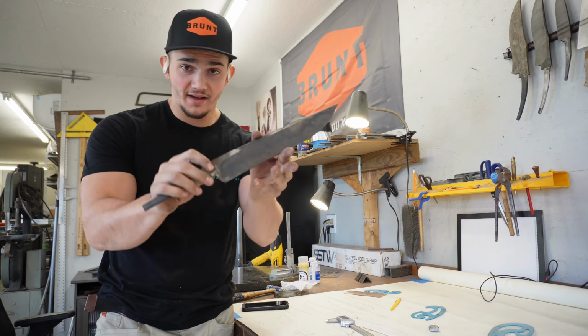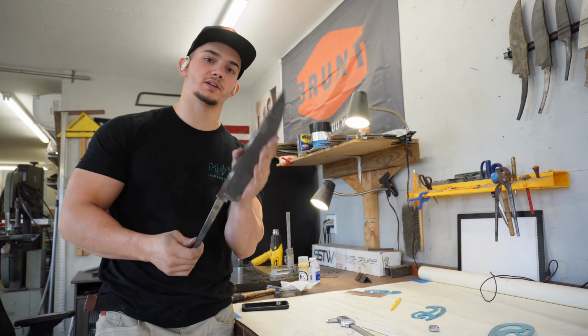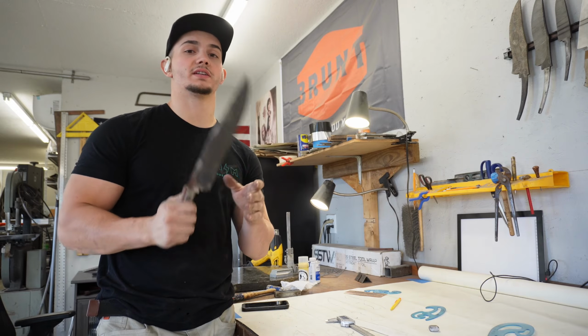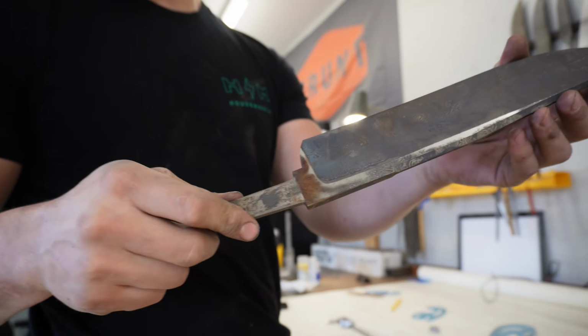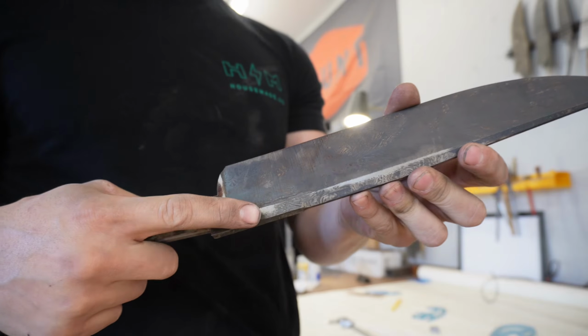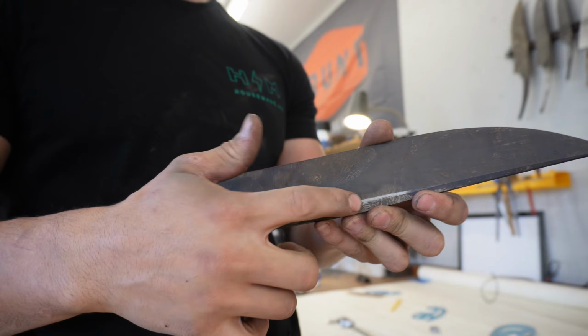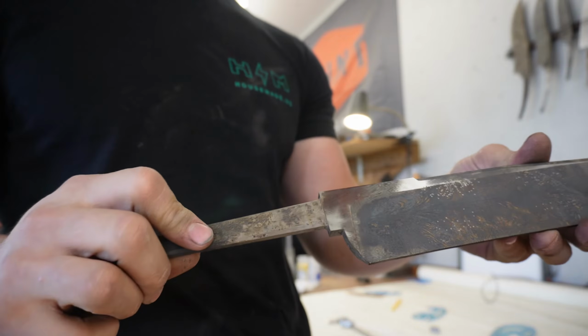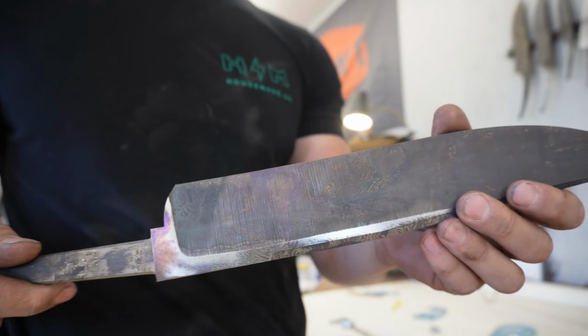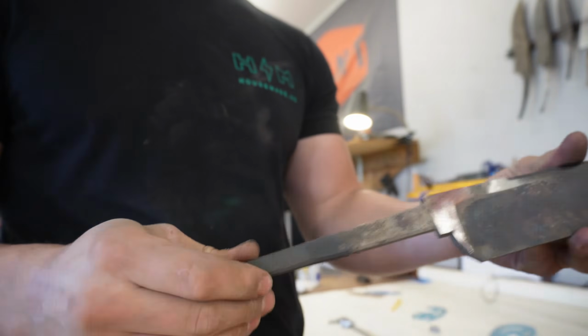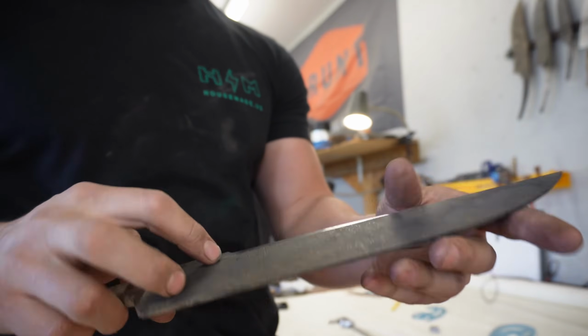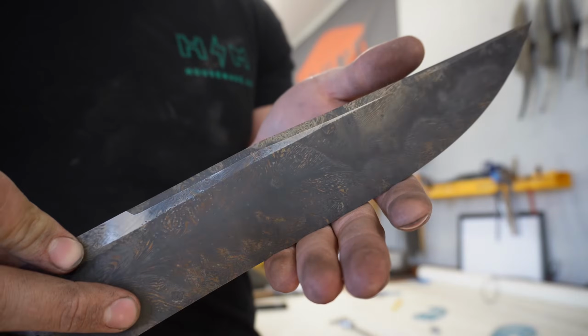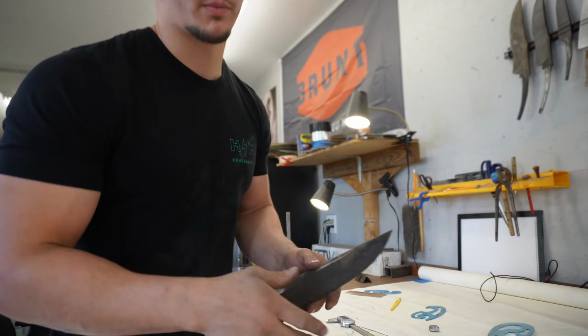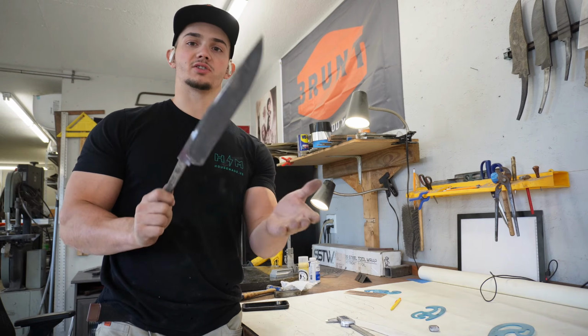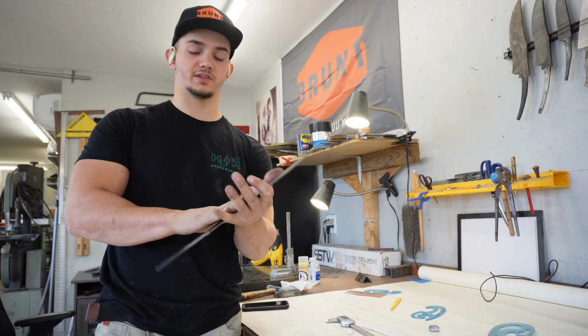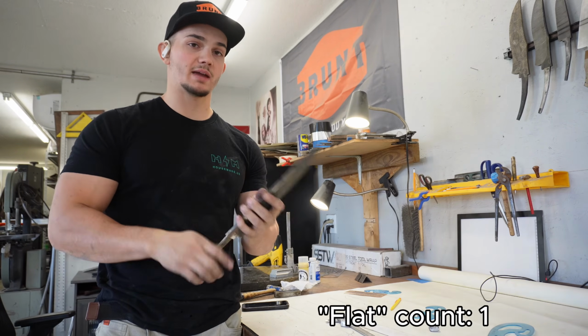All right, guys, so we have the blade out of heat treat, quenching and tempering, and it is now a hardened blade. Did get a little tiny bit of warping. I have simply put it down on a surface plate with sandpaper on it, so you can see those points of contact. Just a tiny little bit of warping going on there, but nothing that can't be ground out. And I also used my carbide tipped hammer a little bit right there to kind of fix a slightly larger warp that had formed. But we are now ready to start surface grinding this thing and getting the surfaces nice and flat, and that's how they will stay before hand sanding.